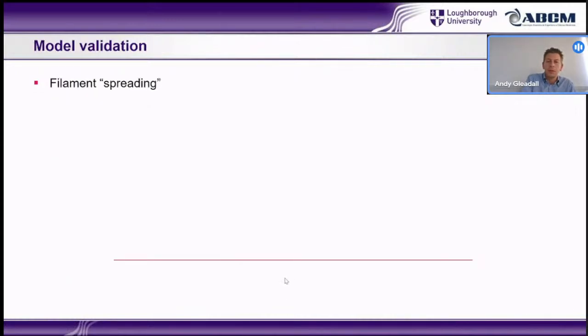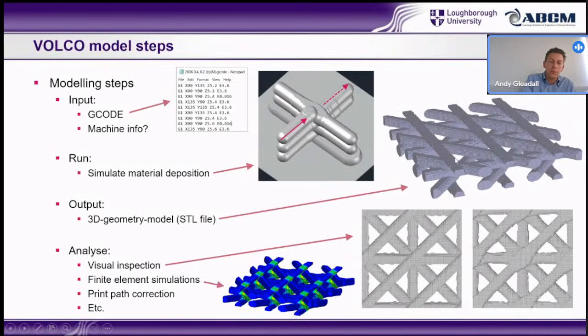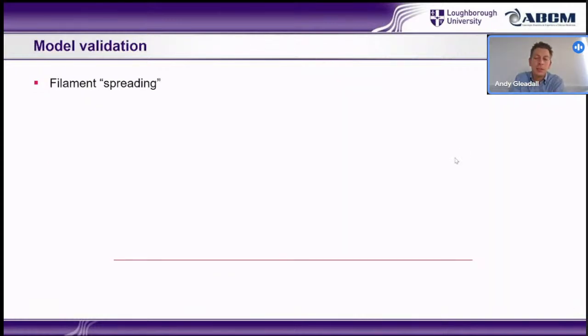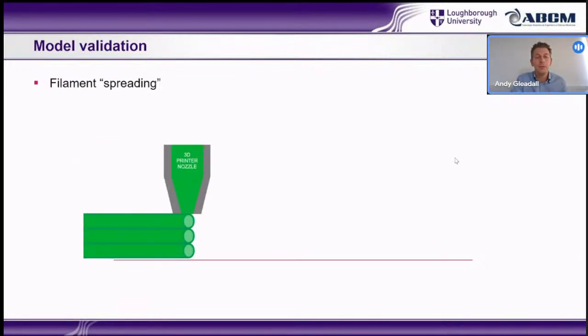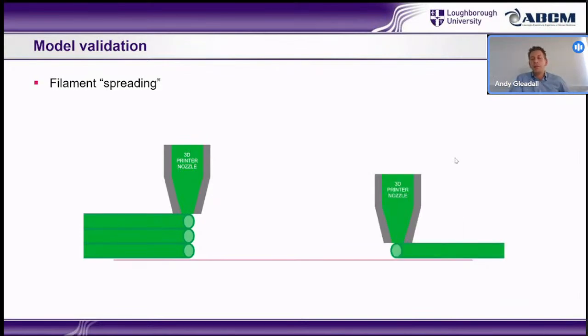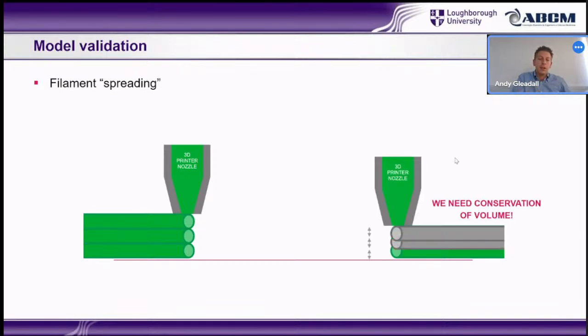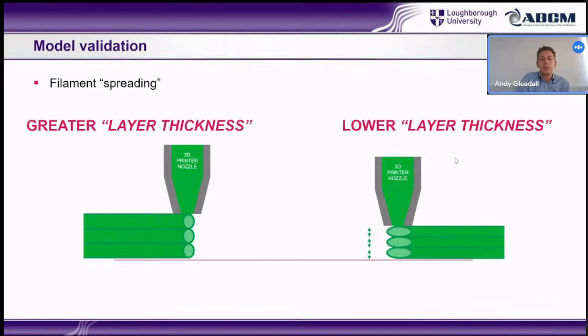One key thing that is always very important is the amount that the polymer squishes as you deposit it, and this is a good way to test whether the simulation was working. You normally print layer by layer, filament on top of another filament. That's all fine. If you do the same again, but you don't leave as much space between the layers, then you've got interference between them. We know we need conservation of volume, so the filaments will actually expand and become wider, because there's not enough room for them to take this tall cylindrical shape.